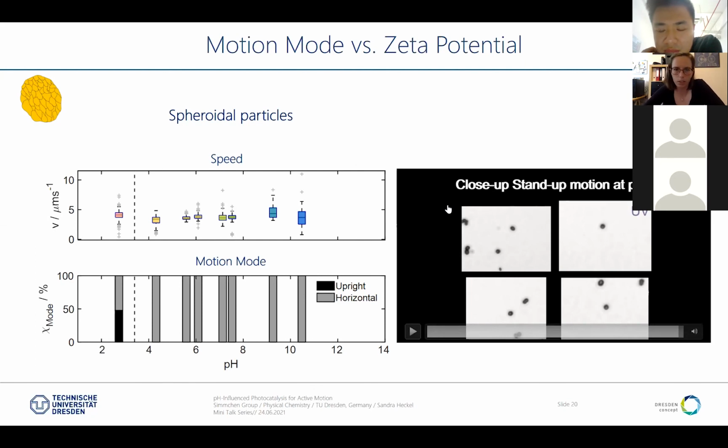Yes, we wrote about this in the manuscript, that when the particles are charged positively, then hydrogen ions are adsorbed to their surface, and then we get these clusters. And then I think what we talked about is that the dissociated hydrogen peroxide needs to get to the surface to actually be degraded. So the mechanism of peroxide decomposition involves very much hydroxyl radicals. They cannot get to the surface anymore, really, because we have these clusters, and that's why this hampers the peroxide decomposition.